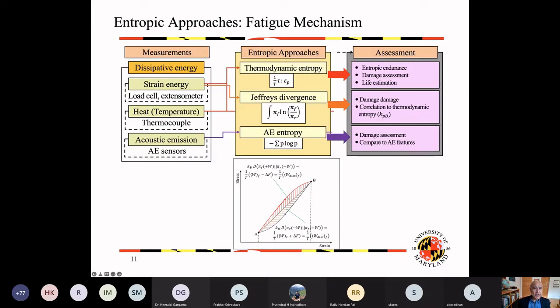So if I look at actually a few of these, if you look at dissipated energies, as I said, thermodynamic, I just showed one way to describe it, but it's not the only way. You could also use statistical mechanics and find the entropy, which is this form. Of course, some of our past papers have focused on this. The Jeffreys divergence in finding entropy, statistical mechanics entropy. The difference is that you just find the dispersions of the material rather than the thermal impacts or thermal dissipations, such as the thermodynamic, such as this thermal force of stress and strain together.